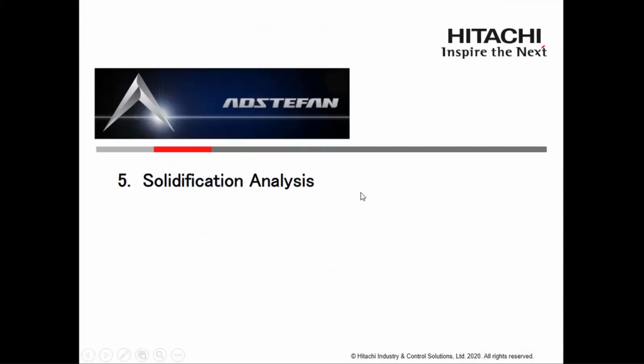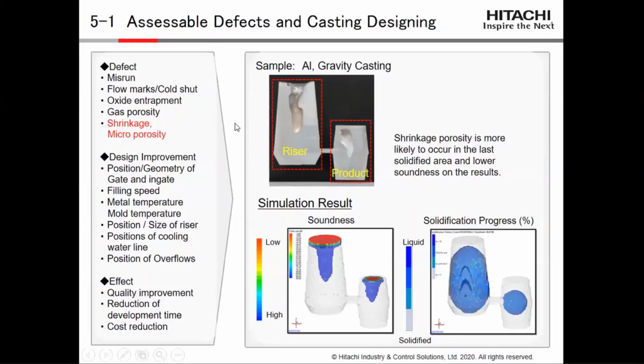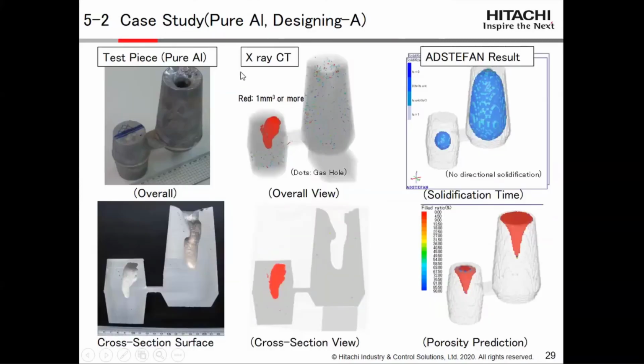Next, it's about solidification analysis. In the solidification process, the typical casting defect is shrinkage microporosity. As the figure shows in the product area, porosity is happening, so it is a phenomenon that we are not hoping for. And by doing simulation, we can predict the possibility of generating this defect. So it shows a simple case study using this test piece. In this test piece, as a conclusion, the product generates porosity as shown in the figure.